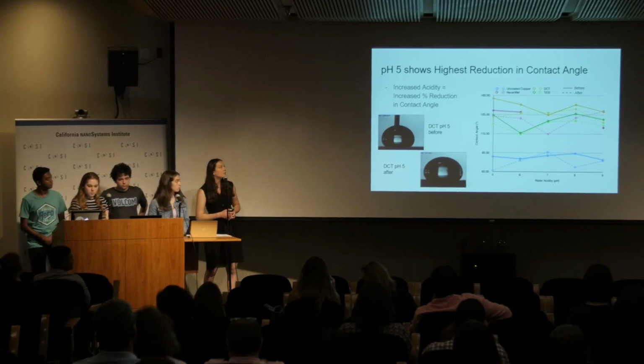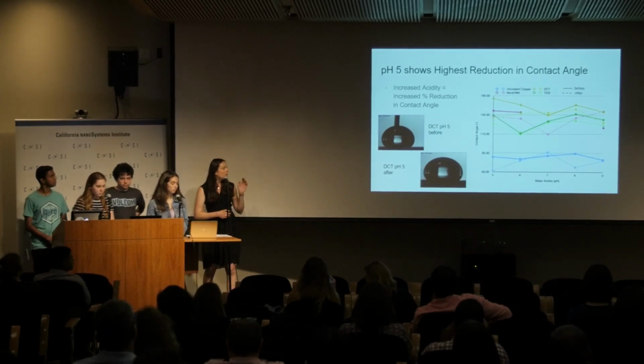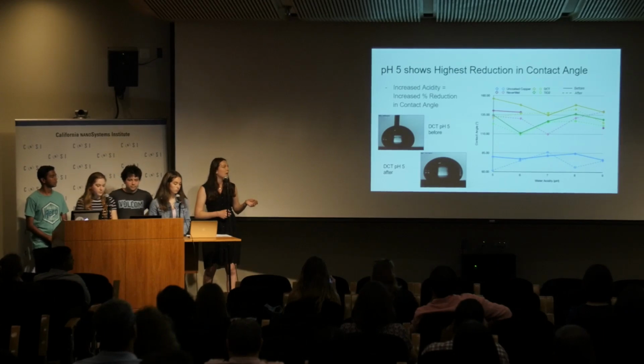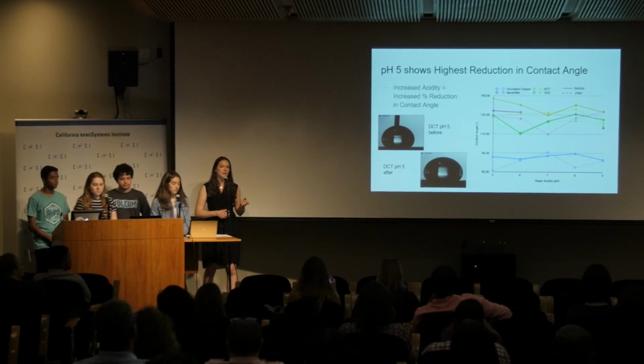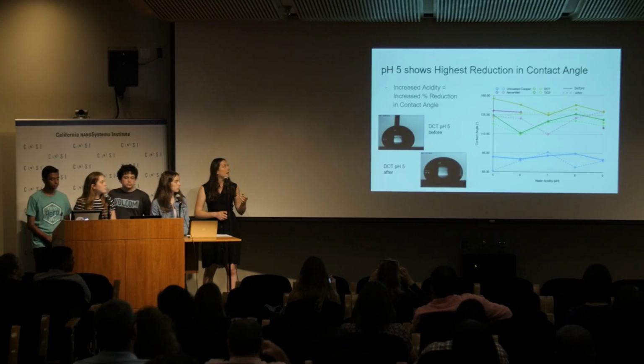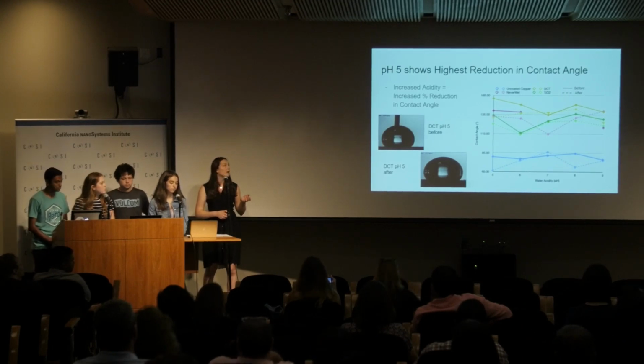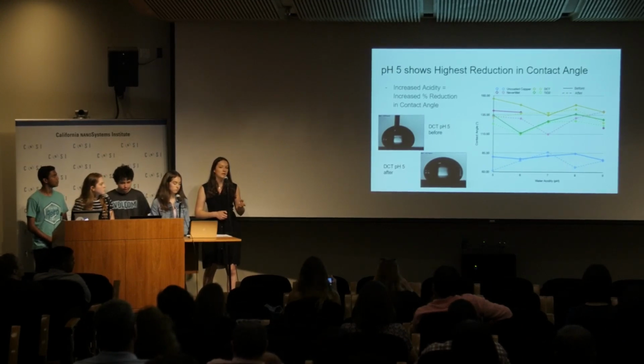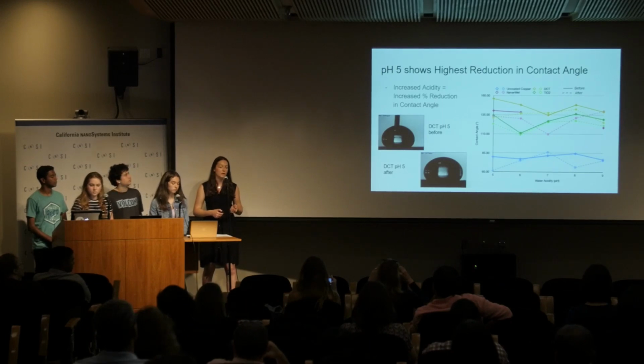And so then we also plotted the contact angle against each pH. And what we found is that at pH 5, there was a large decrease in contact angle before and after submersion. So that might mean that increased acidity increases the reduction in contact angle and thus increases corrosion.